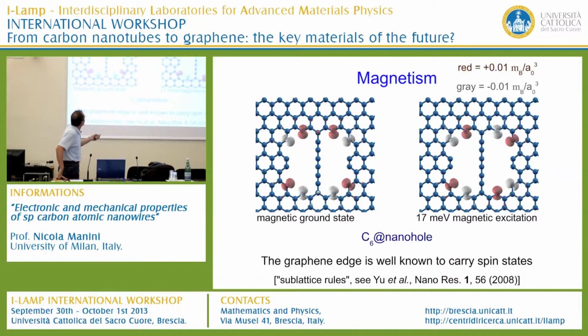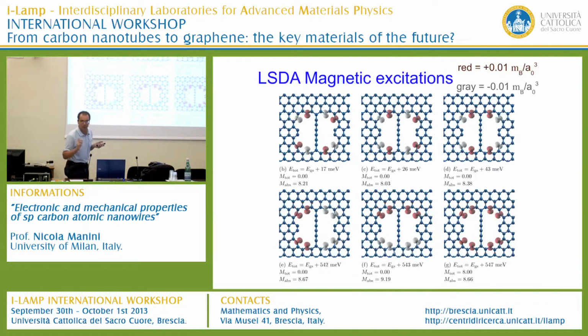For example, this will be a situation where this spin has flipped and a few others have. So you see that these magnetic excitations will have a very small energy, so one can invent, if you want, a spin-only model to describe them. These will be other magnetic excitations, and those can be described in terms of some J interaction, describing the coupling between spins at different edge states.